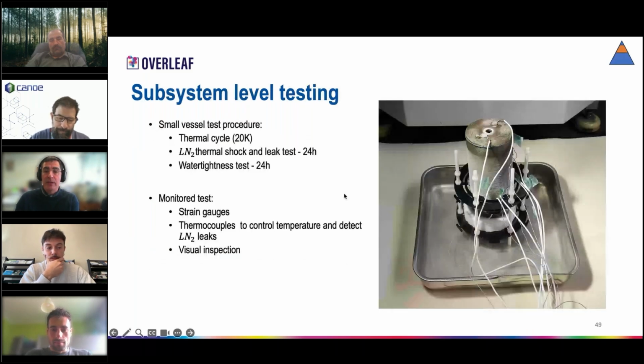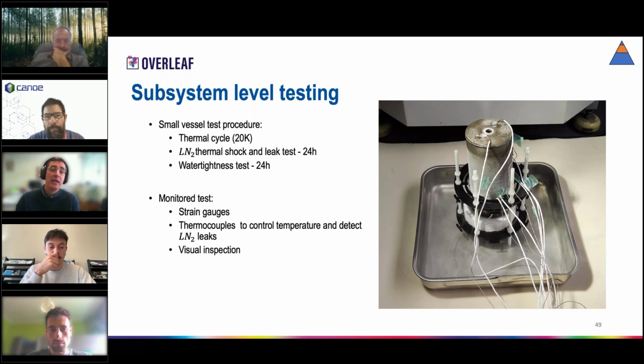Finally, for the third level of the pyramid, that was the subsystem level testing, Aymen manufactured a small vessel that was tested in our installations. And what we first did was perform a thermal cycle to 20 K to see if with this thermal cycle we created some damage on the matrix. Then we performed a thermal shock and a leak test, and finally a water tightness test. The objective was to check different singular points and to see if there was tightness of this vessel.